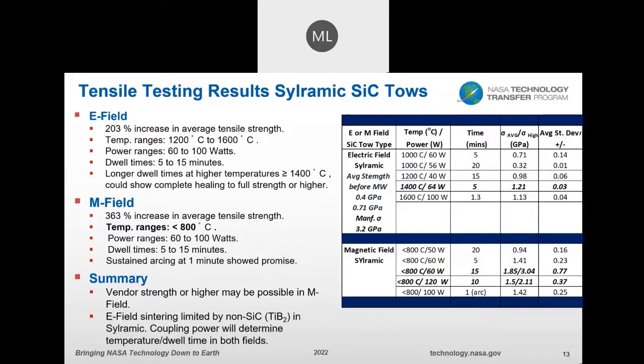So when you look at this, you can see that we're starting to get, well, it was not to full strength. We think that we could get to full strength. That's what I meant to say, excuse me. And then when we look at the magnetic field, we had a much higher increase in average tensile strength. The temperature range is less than 800 degrees C.